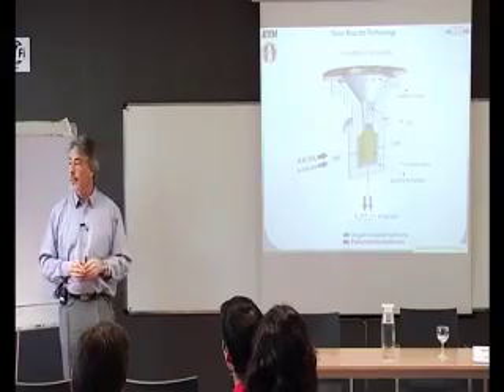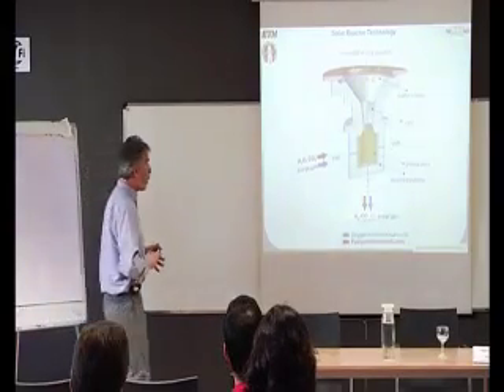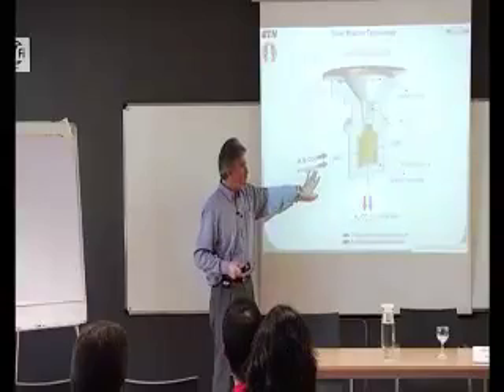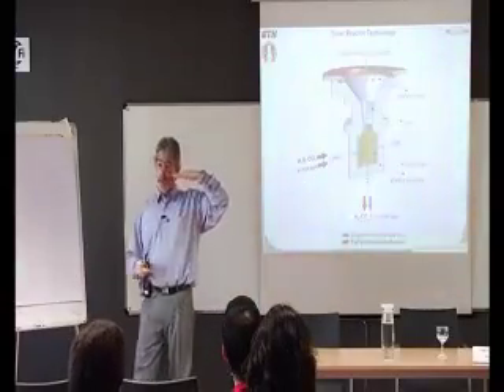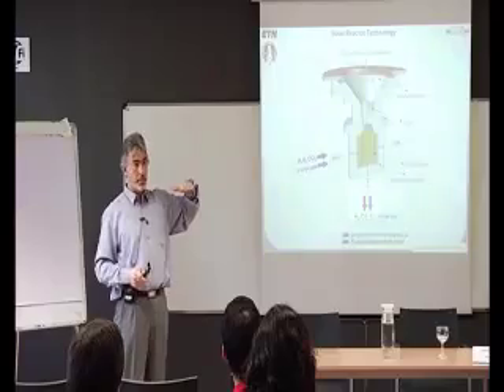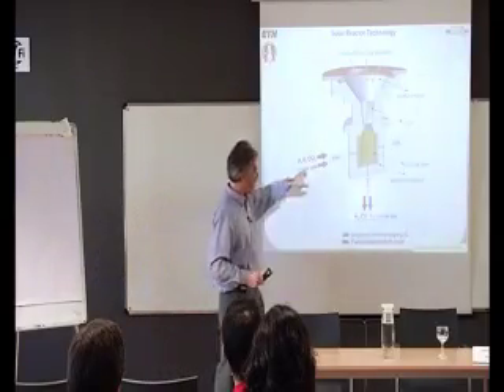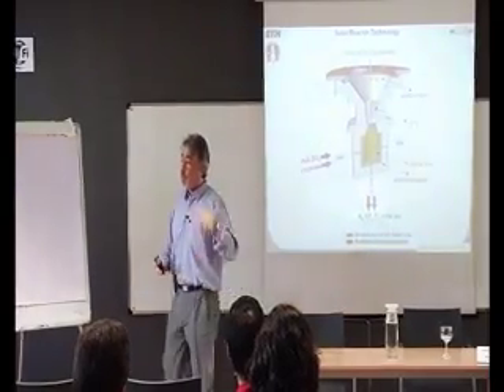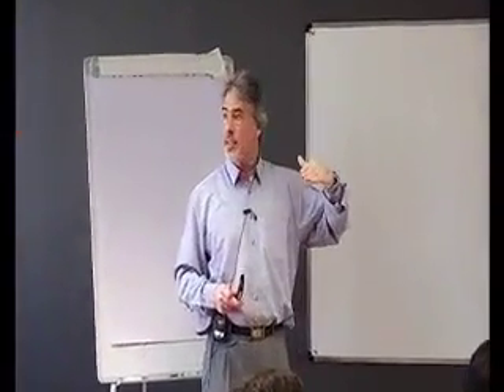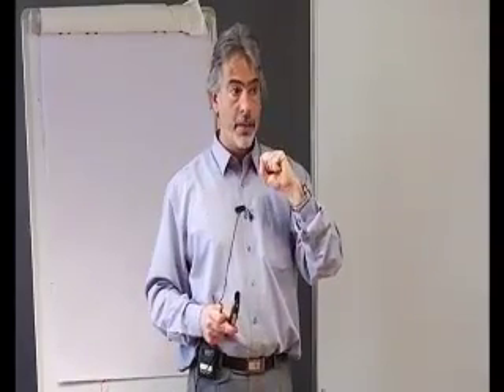¿Se podría llegar a eliminar el argón? And the argon, to eliminate the argon, we will have to go to higher temperatures. For example, 1700 degrees Celsius. And then we don't need anymore to recycle the argon. But at 1700, we are already reaching the limit of what the ceria can do. As we go to 1700 degrees Celsius, we lose ceria metal in the vapor phase. Cerium metal, sorry, in the vapor phase. So we are just reaching the limit of the temperatures that we can operate.